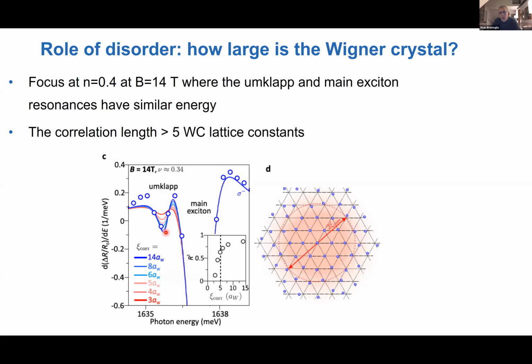The position at least scales correctly with the magnetic field, or with the density of the electrons. We only did it at 14 Tesla, so I cannot talk about scaling of the size with the magnetic field, if that's what you mean. As I tried to explain, when the resonance is far off from the main exciton, it's very hard to fit the line shape with good accuracy. Beyond 12 Tesla we can get to this resonance situation, and we have a limited magnetic field value. So honestly, we only did it for 14 Tesla, and the maximum field we can have is 16. Okay, thanks. Thank you.